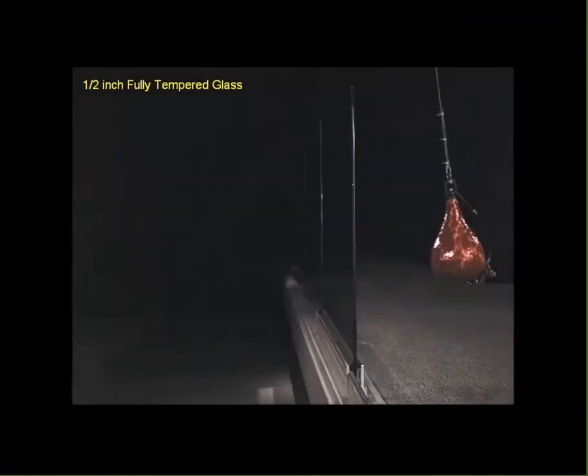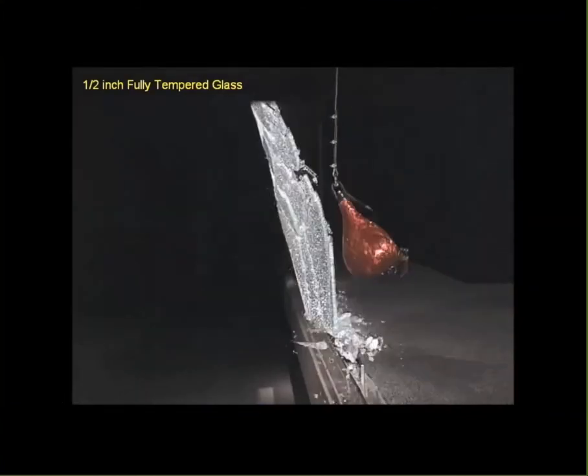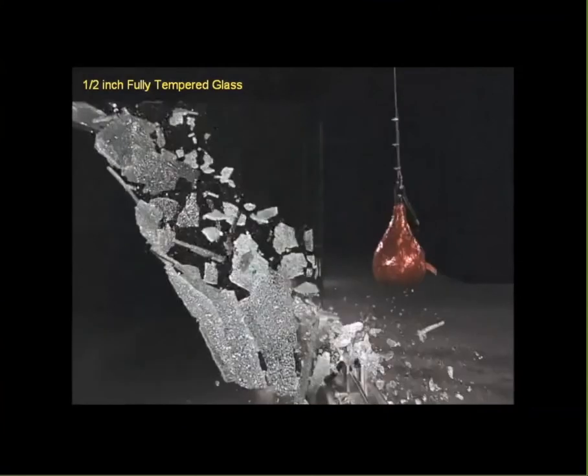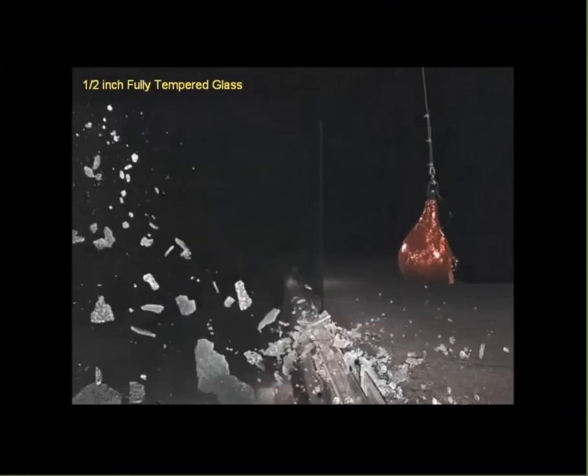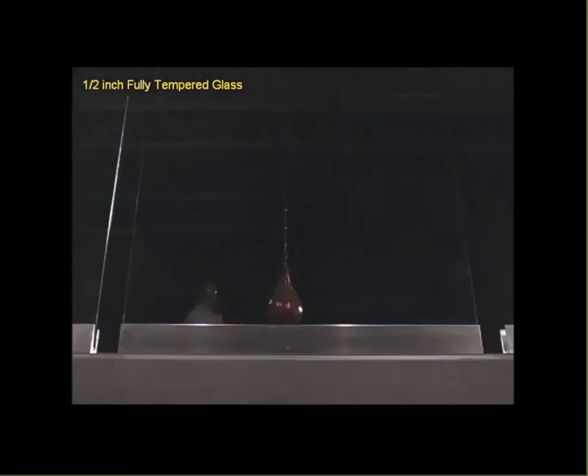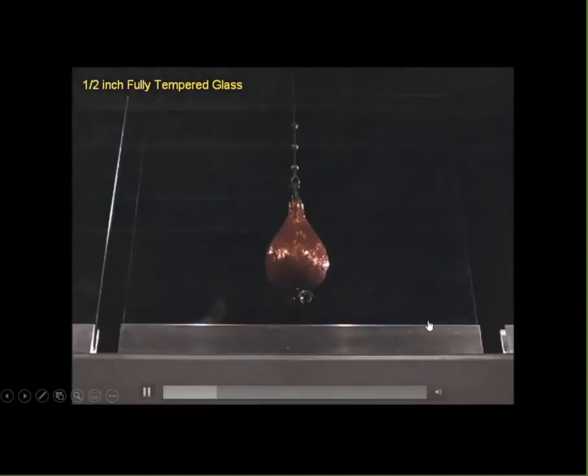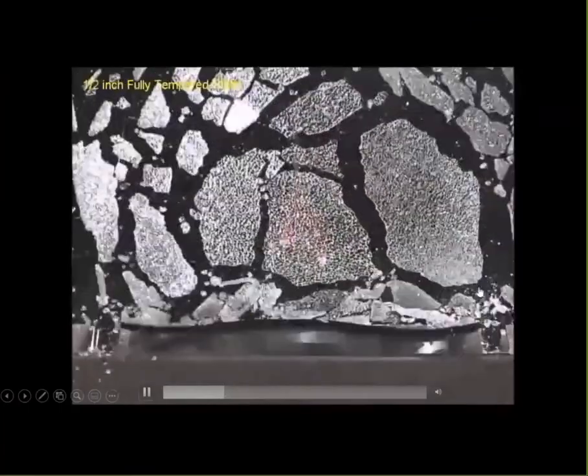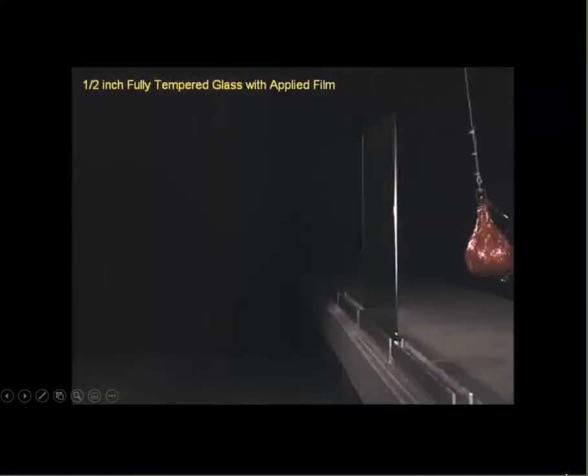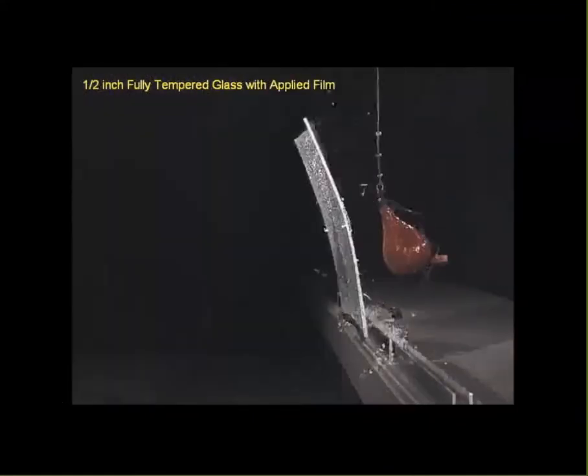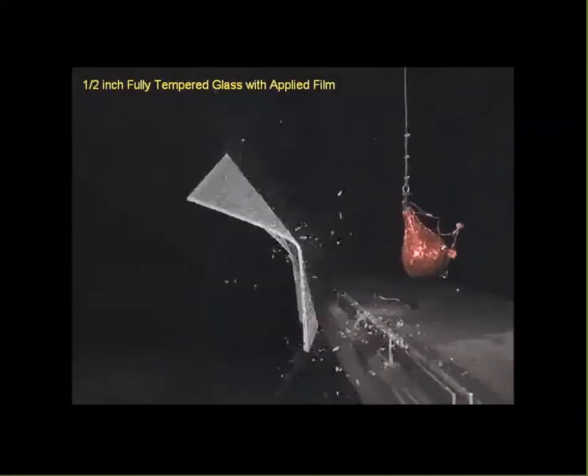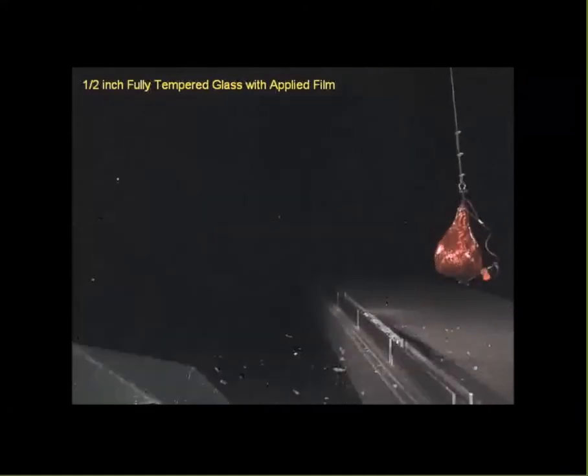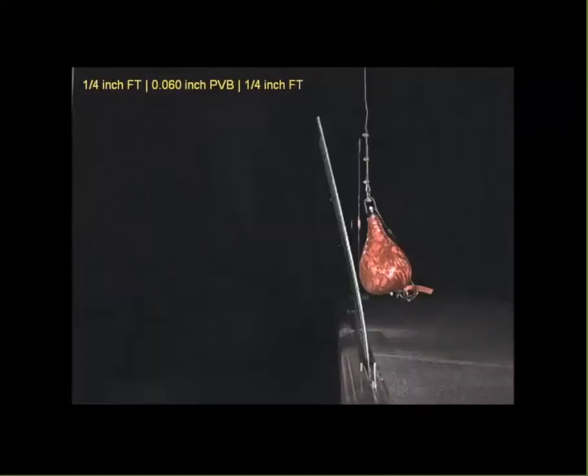So what does it look like? This is your half-inch tempered glass after impact. You see how it breaks. I think most of you are probably familiar with that. It's supposed to break into small pieces, and it does. But if you look at some of these big chunks that are agglomerated before it hits something else, if a half-inch piece of glass that size hit you on the head, it would not be pleasant. If you put film on it, it holds the glass together very well, but now you have one piece of glass falling. It's very dangerous.